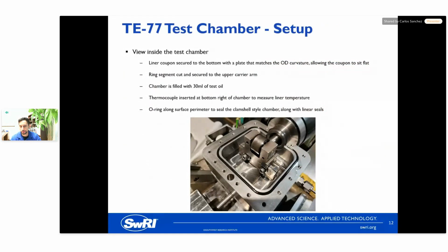As you can see, it's a typical ring and liner setup. We have our carrier arm at the top. The liner coupon is set up at the bottom. It sits on this little saddle piece that matches the curvature, the outside diameter of the liner, so that way it actually sits flat. And we just do our typical alignment procedure.